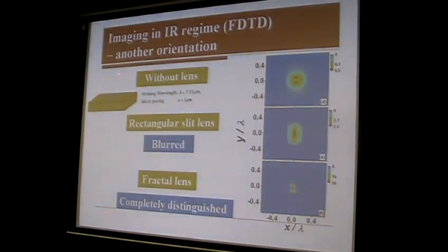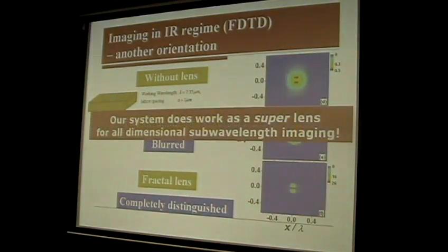Now let me study another orientation. Before, the orientation was like this; now the orientation is like this. Still without a lens, for this orientation, the two images cannot be separated. For the rectangular slit lens, because it does not support surface plasmons along this direction, in this case it cannot separate the two images, or it just blurs. For our fractal material lens, you can still see that these two images are clearly distinguished. So the conclusion is our system does work as a superlens for all-dimensional subwavelength imaging.